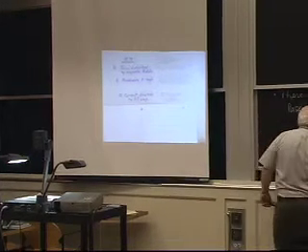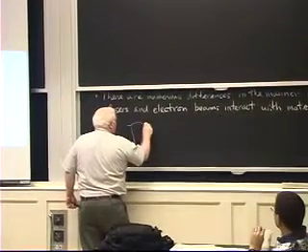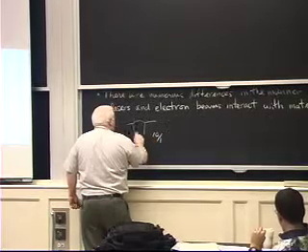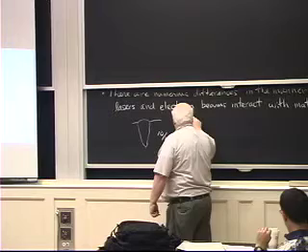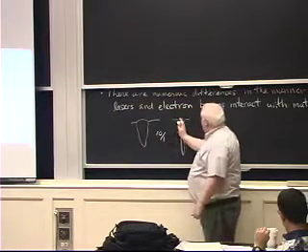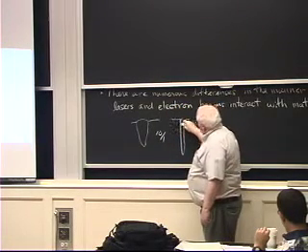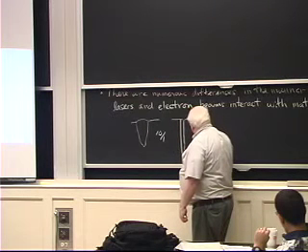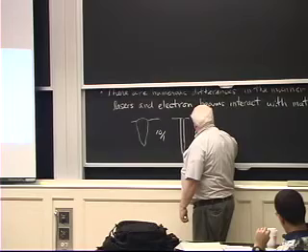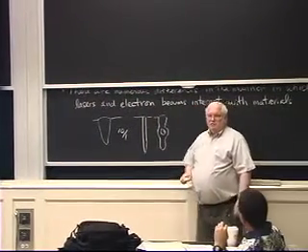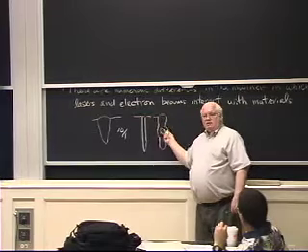It's not practical. In fact, and this might actually be the next point, the greatest depth to width ratio you want for an electron beam is about 10 to 1. The reason is, if you make something that's very thin like this, not only will you miss the joint if you're off by some angle or some translation, but if that thing has any tendency to form a shape like this, you're going to end up with a solidification defect right in the big areas, because the stuff shrinks from the sides in the bigger area.